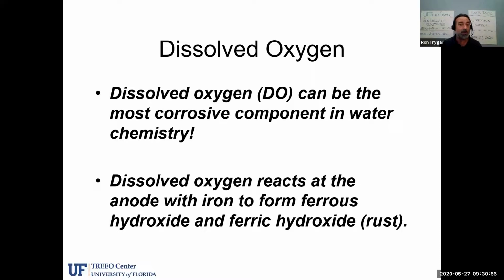But if you have electrolyte or water with dissolved oxygen in it, you will speed up the corrosive effects of that water column. So dissolved oxygen reacts at the anode with iron, and it forms ferrous hydroxide and ferric hydroxide, which again is known as rust, and rust is the tubercle, and the tubercle is known to get bigger and bigger, and that whole process is called tuberculation. And then finally, the wall thickness of the pipe gets thinner and thinner at the anode, and then we have a leak in the pipe.